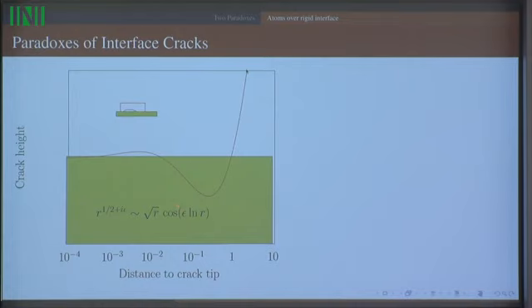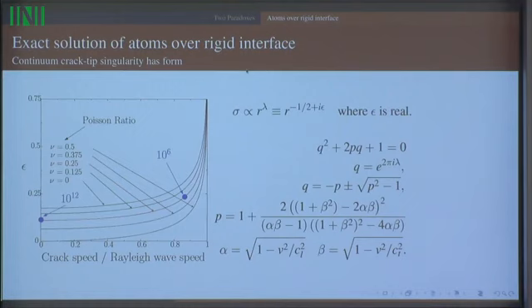But the thing which is puzzling about that is that it seems to indicate that the upper solid should penetrate the lower solid, because it's wiggling up and down. Granted, on a logarithmic scale, but even so, that's what it's supposed to do. So for this and for some other reasons as well, the idea of studying, particularly moving things of this sort, was not always viewed favorably. And there were debates in the literature about whether something like this was a good starting point for studying any physical phenomenon.